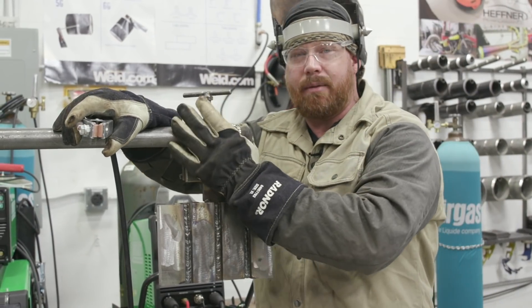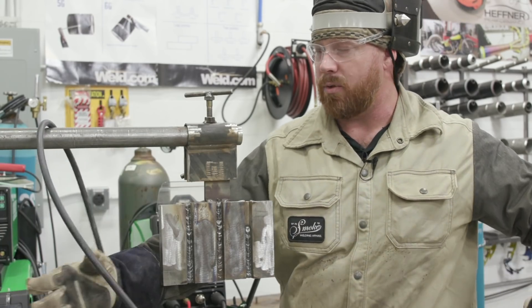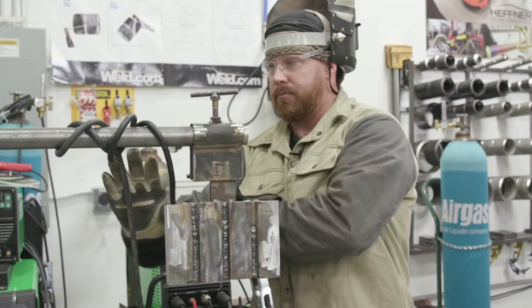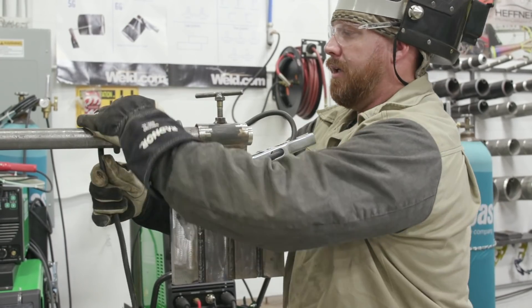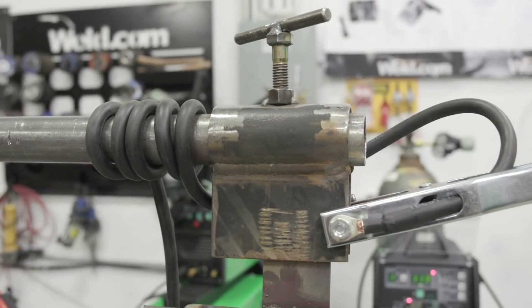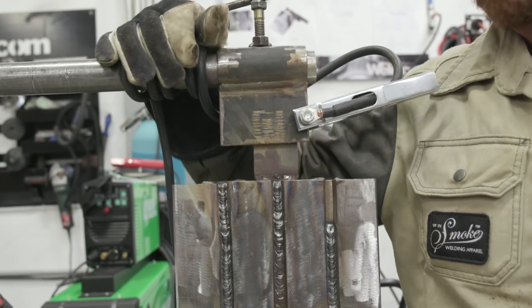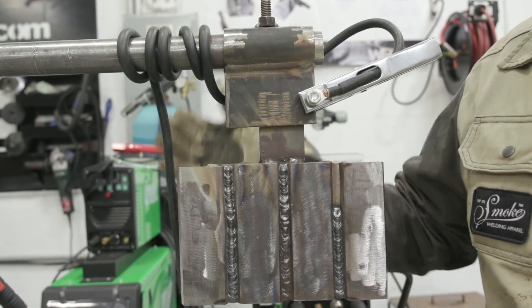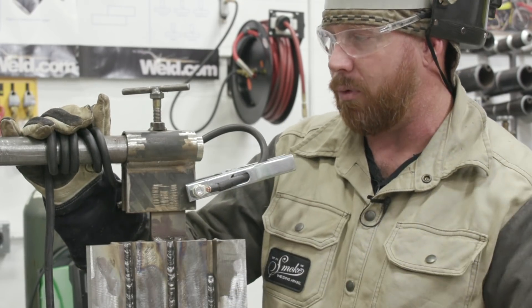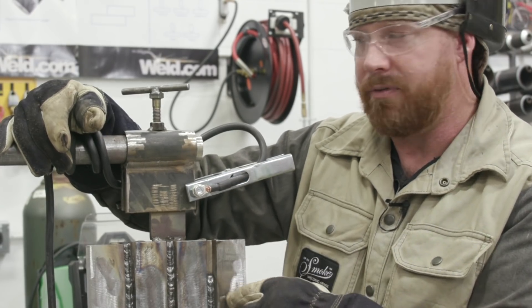For the third method, take your workpiece clamp and simply wrap it around the part you're working on — obviously out of the welding area so you don't burn the coating. Just wrap it around a few times to make a little coil. From what I'm told, it kind of disrupts the magnetic field created by the electromagnetic arc blow. When using this method, it shouldn't matter much where you put the workpiece clamp as long as you can get it wrapped around the fixture or weldment. If you can't wrap it, go back to clamping to the bottom and welding away.